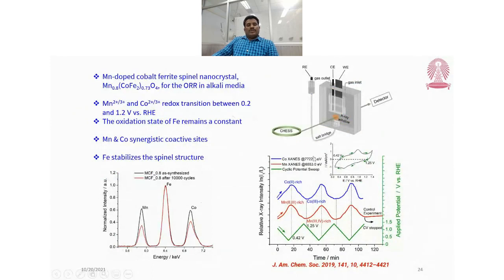One report used these techniques and published in JACS. They synthesized manganese-doped cobalt ferrite and evaluated ORR reactions. During this reaction, manganese and cobalt interchange their oxidation states during the redox process. However, the iron oxidation state remains constant. So they concluded that the manganese and cobalt are synergistically active sites to accelerate the ORR reaction, and the Fe stabilizes the spinel structure.